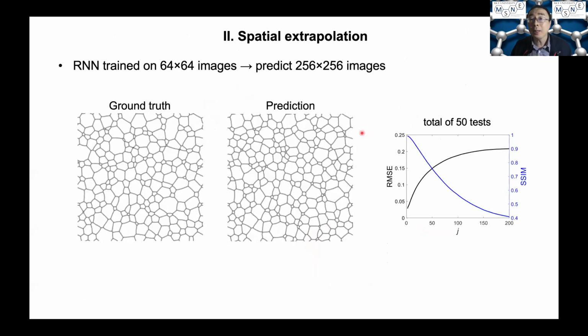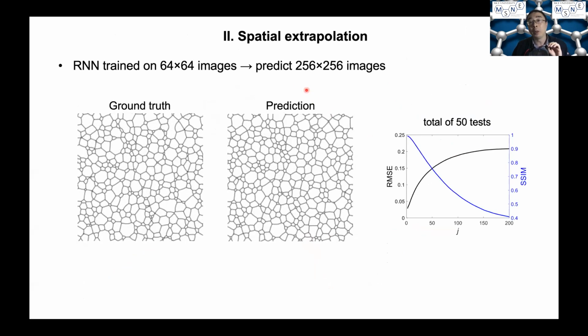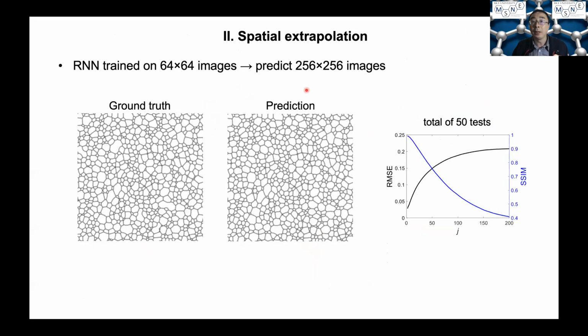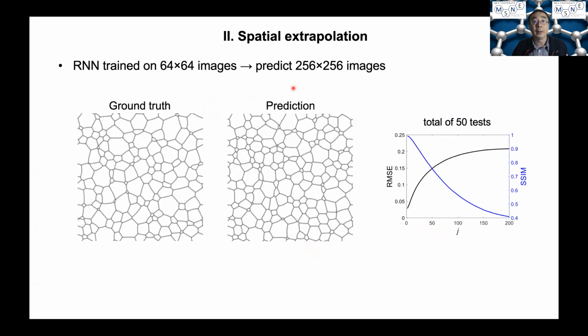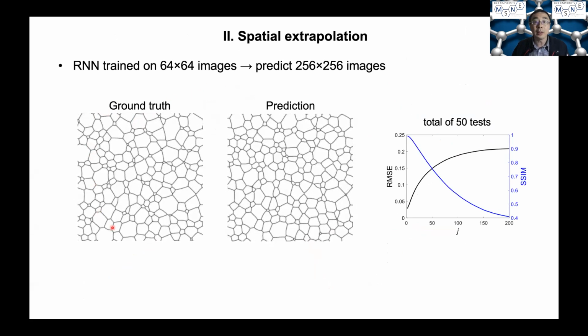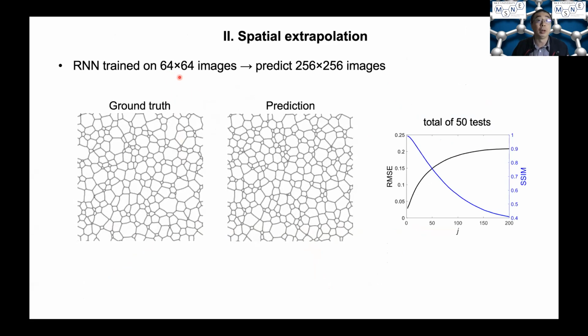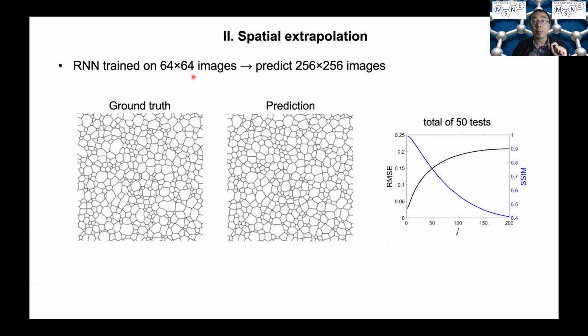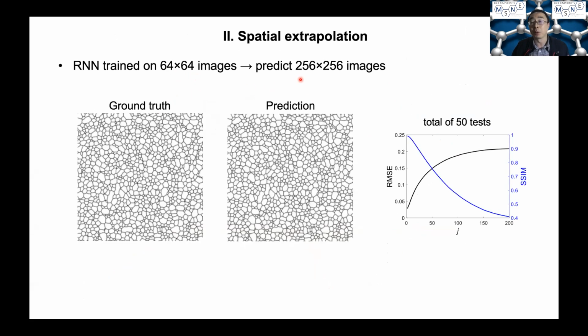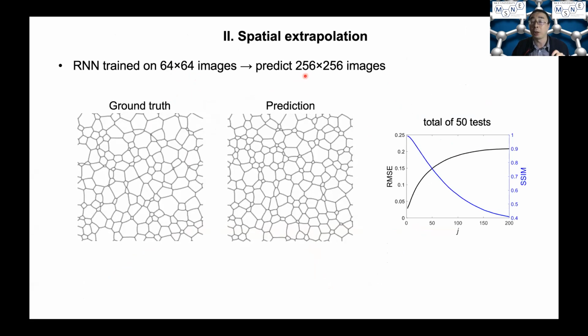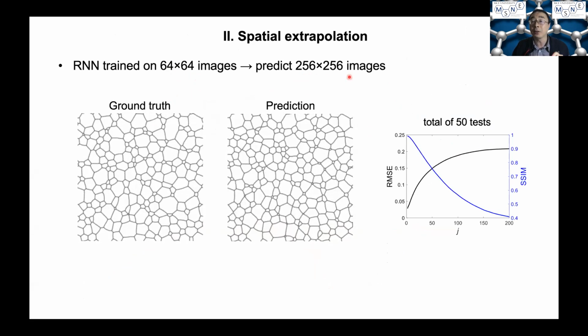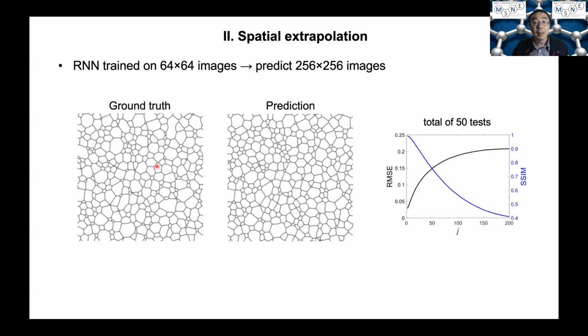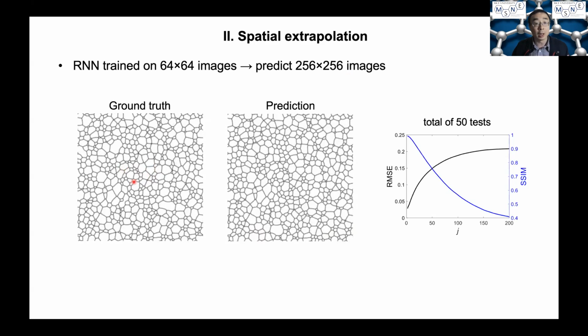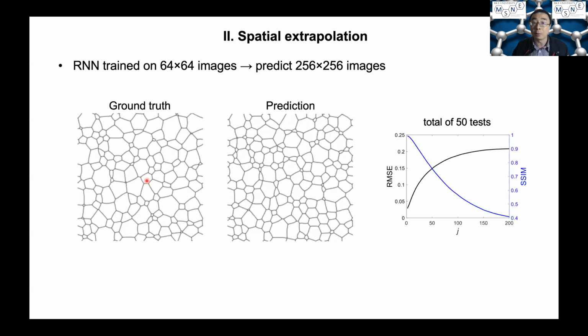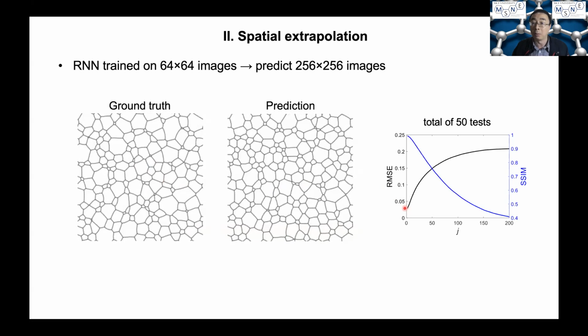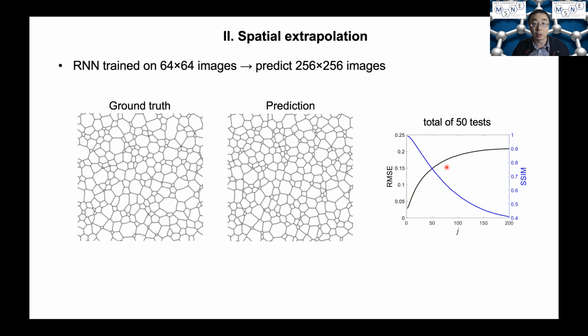Right? In the second type of test, we challenge the model with its ability in extrapolating the learning spatially. So what I mean is we initially train the model on small microstructure images of 64 by 64 pixels. And then we apply the trained model to predict the grain growth process in a larger system of 256 by 256 pixels. So that's 16 times larger in area. But we found the performance of the RNN model is as good as its prediction on the smaller domains, both in terms of the pixel-wise comparison and also in terms of statistical properties.